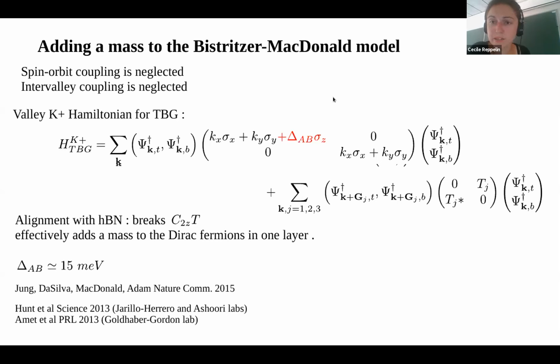This is a little bit subtle because in principle, since the two lattice constants, the one of hBN and the one of graphene, are not exactly the same, you should basically add a plus delta AB sigma Z on one zone of the superlattice, and then half a period further, you should have a minus delta AB sigma Z. But it turns out that effectively, this is not what happens. Effectively, it's enough to just add this one uniform term on the whole lattice.